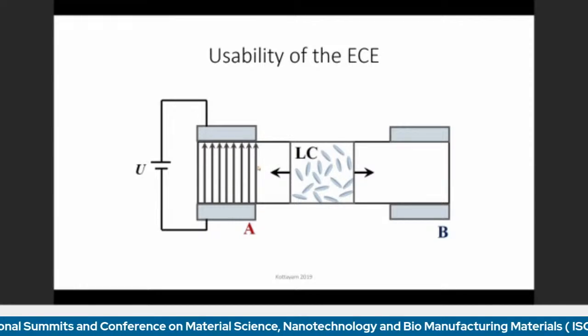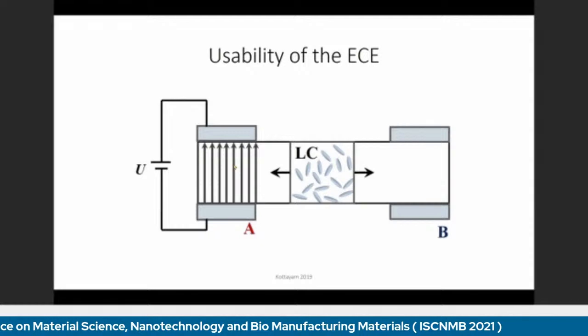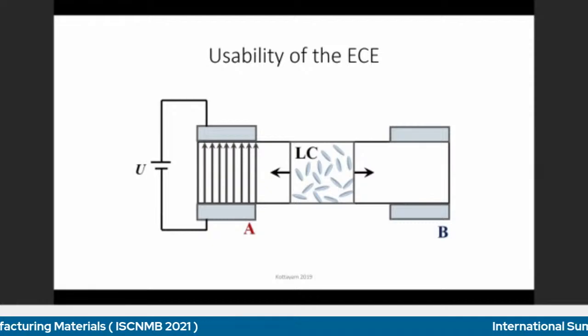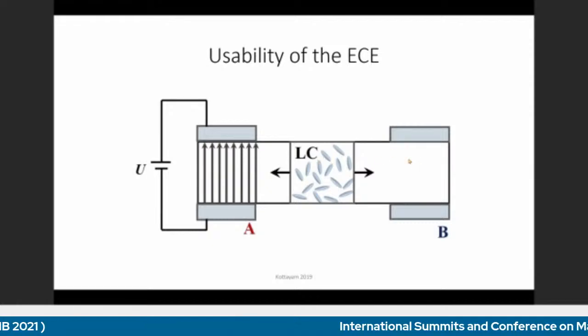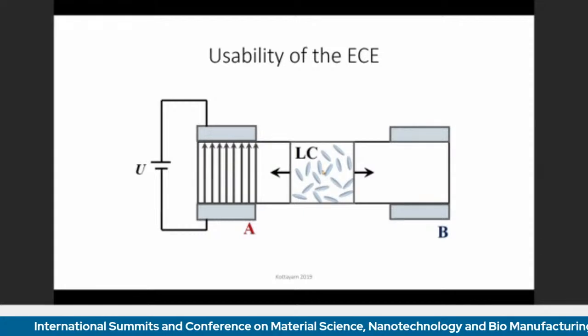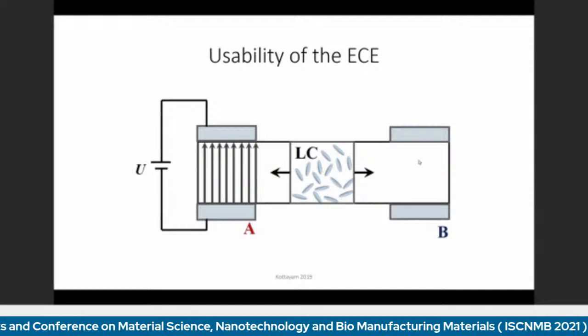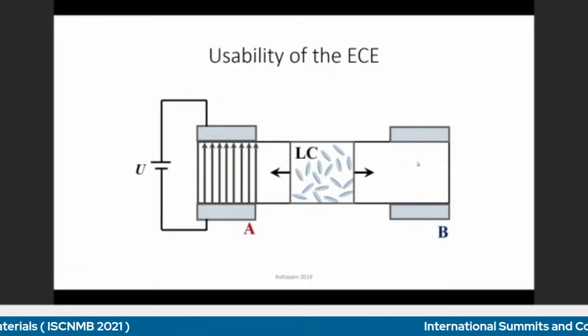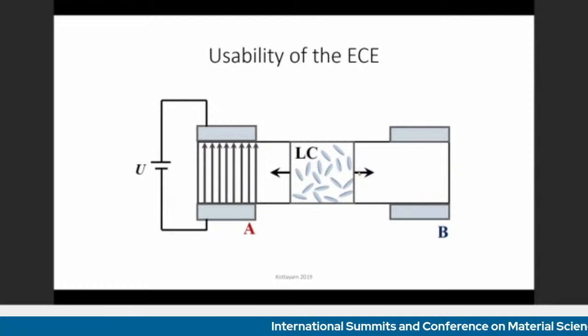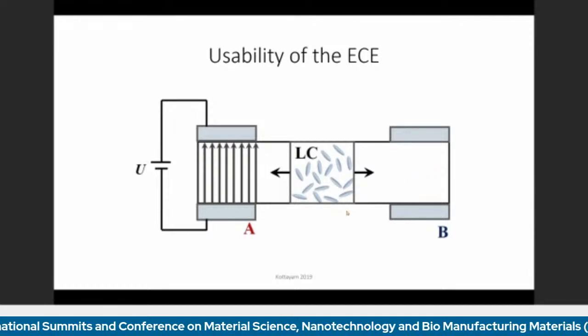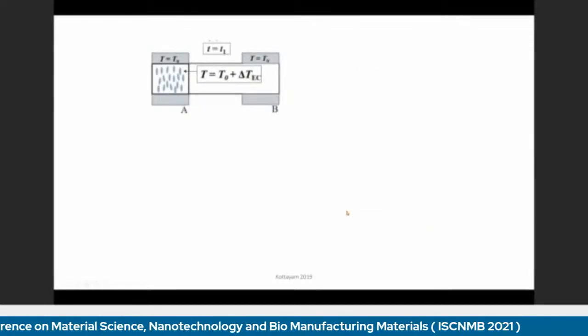So what happens if we shift them to A? That means that we decrease the orientational entropy and the thermal part of the entropy increases, so we get heat. And if we put it to the state B, then the orientational part of the entropy increases. Therefore, because the sum has to be zero, the temperature part of the entropy has to go down. So we have a drop of the temperature in the LC. If we perform the shift adequately with the frequency, then we can get the difference between site A and site B even further.